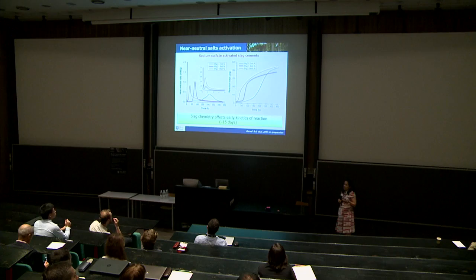In this case, we can also see significant differences in the isothermal calorimetry when we use slags with different contents of magnesium. But what's really interesting here is that the main differences in precipitation of reaction products are identified at very early times of reaction. Once the material has stabilized, we can reach comparable degrees of reaction independently of the chemistry of the slag we're using.